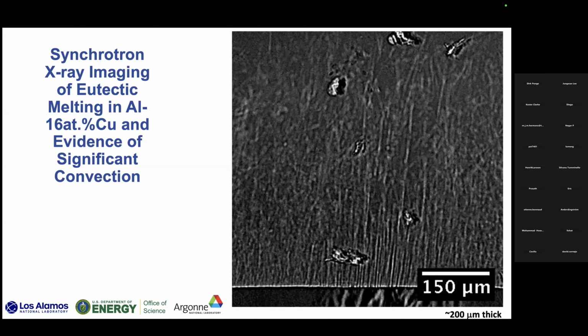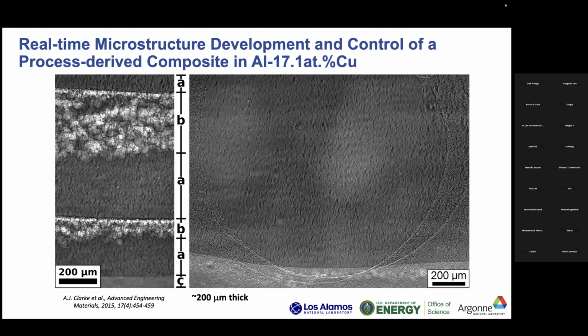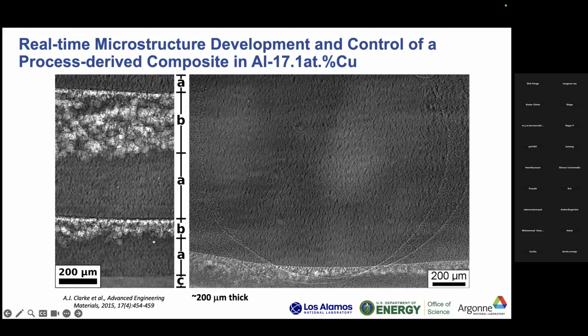Taking that a step further, having the benefit of seeing microstructures while we process them, this is an example of what we call an artificially process-derived composite in an aluminum copper eutectic composition. What you're seeing here is a solid liquid interface that we've stopped in the field of view, and we're going to do a series of melt back and solidification steps. Up on top is our solidified eutectic, and then you're going to see a melt back of the interface. This is again on the order of about 200 microns or so. So here we're melting back the interface.